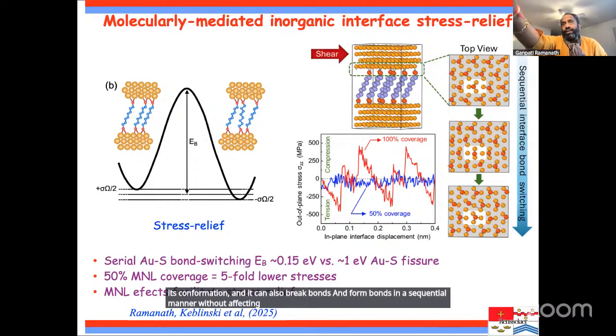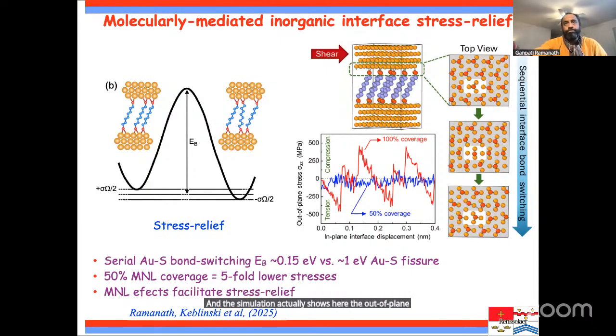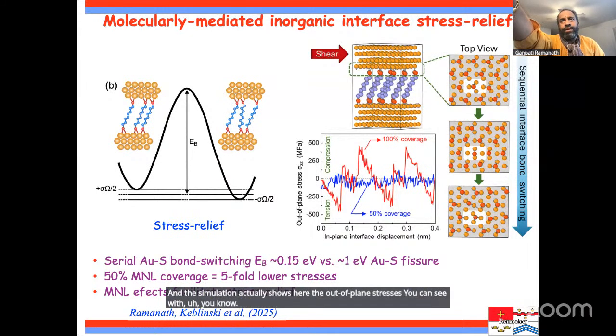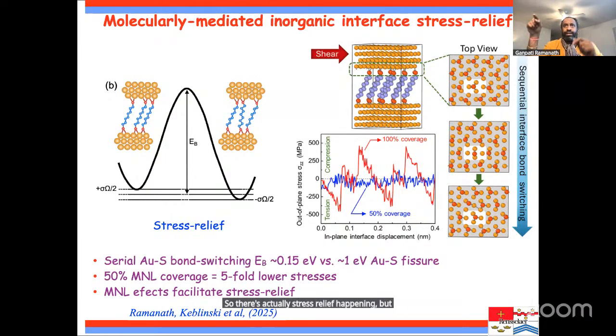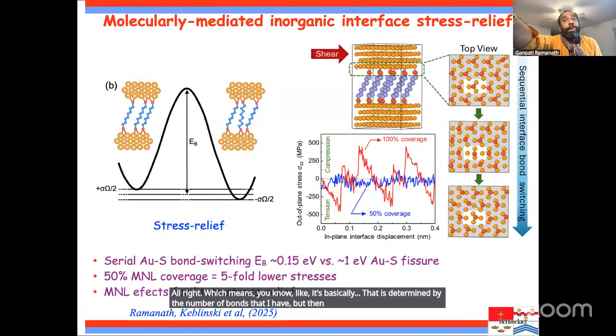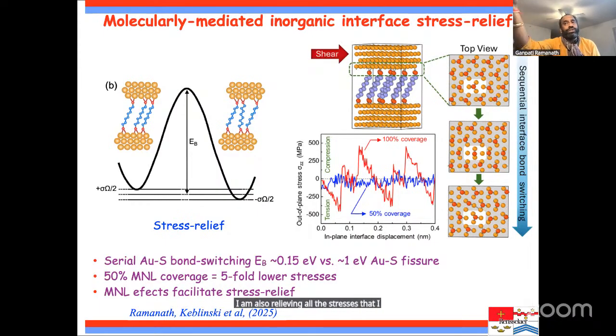without affecting adhesion. And the simulation actually shows here the out of plane stresses. You can see the red curve going up and down. For 100% coverage, there is bond breaking, bond reformation, bond breaking, bond reformation. So there is stress relief happening, but there are local stresses that are going up and down. But if I have a 50% coverage, which means I'm creating a defective molecular layer, now my adhesion is decreased, which is determined by the number of bonds that I have. But then I'm also relieving all the stresses that I see over here. There's no stresses that are seen at the interface. So we need to validate this experimentally, and that's what we'll work on.